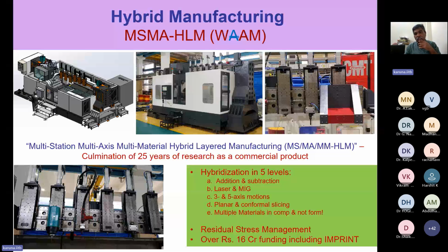And at the right, you see a red colored box. That is our 25 kilowatt preheating system. So you can preheat the previous layer to 500 degrees centigrade or as required. We can go up to 700 degree in this machine. It's a 25 kilowatt induction heating system. So we preheat the previous layer. After that, we do welding on it. So by doing it, we are able to minimize the possibilities of the residual stresses. Instead of depositing on top of a surface which is at room temperature, you deposit on top of a surface which is at 500 or 550 degree centigrade. As a result, the extent of stresses will be less.